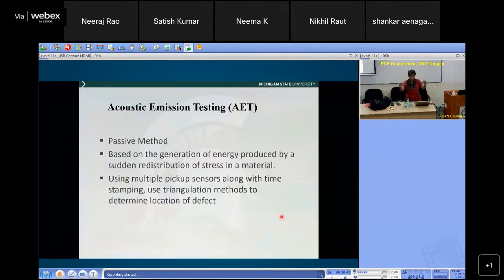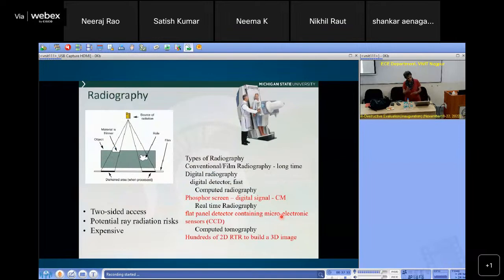If you can embed these continuously and monitor, it's possible. Particularly in aircraft engines, there are so many parts in aircraft which are cyclically loaded, right? That's what causes fatigue, and acoustic emission testing can be used. But basically the interpretation algorithms have to be very complex. Also, with acoustic emission, we don't have an idea of the geometry of the source, and it can have reflection. You get the signal, you have reflection. So the signal, if you've seen it, looks extremely noisy. The crack signal may be embedded in a lot of noise. So interpretation is a problem. Nevertheless, it's a method.